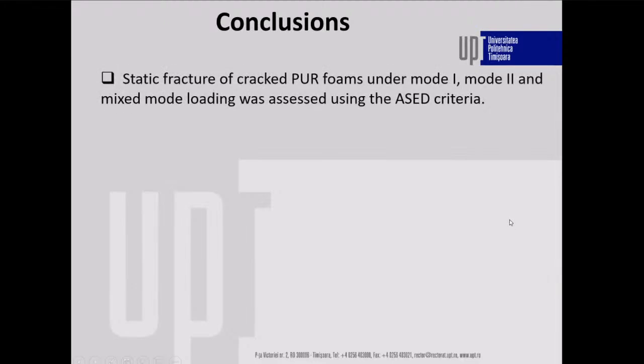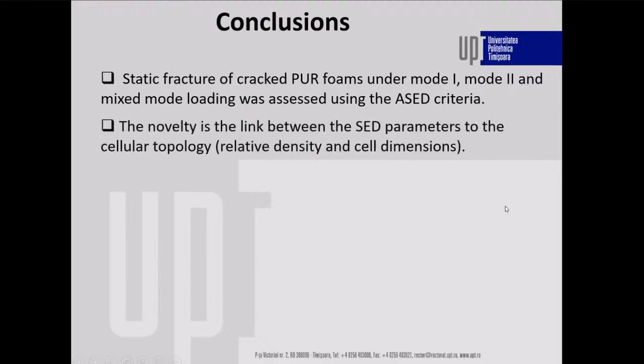So, to conclude, we did some static fracture tests of cracked polyurethane foams under different types of mode mixities from mode 1 to pure mode 2. And we assessed the fracture using average strain energy density criteria. The novelty of this study was the link between the strain energy density parameters and the cellular topology, relative density, and cell dimensions, and the micromechanical predictions of the mechanical properties of the foam.